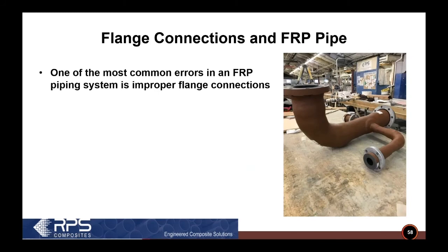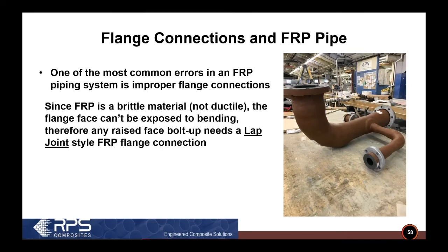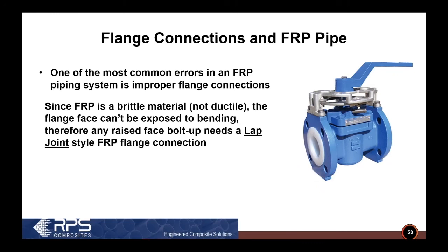Flange connections are also very common in FRP. They have the same drilling pattern that you would use in metallic piping. You do have to be careful though, because FRP is not a ductile material, like we were saying when we were explaining FRP versus metallic. And that means if you have any kind of bending around the flange face, you're going to be in trouble, and you need to use a lap joint style flange for that. So if you look at this valve here, that lining that's in the valve doesn't come right out past the bolt holes, that's going to be a problem if you use a full face flange.